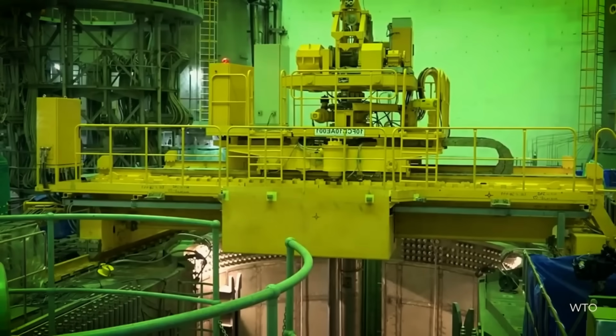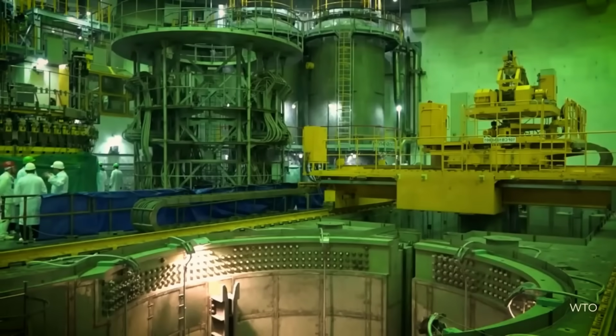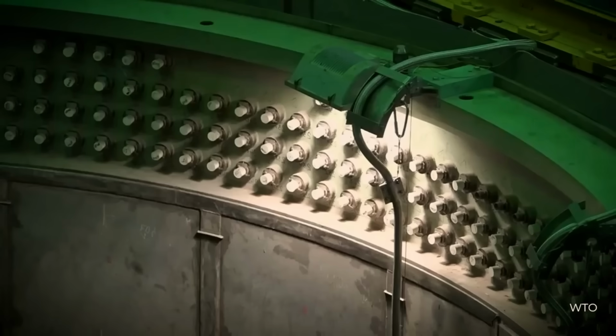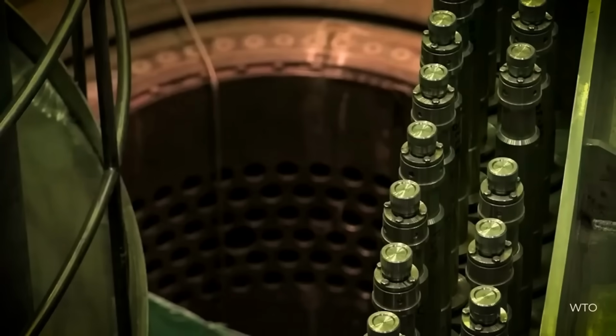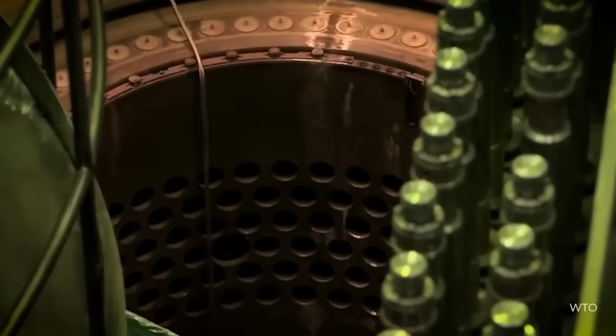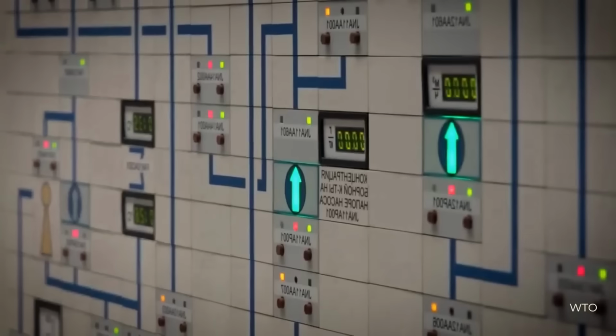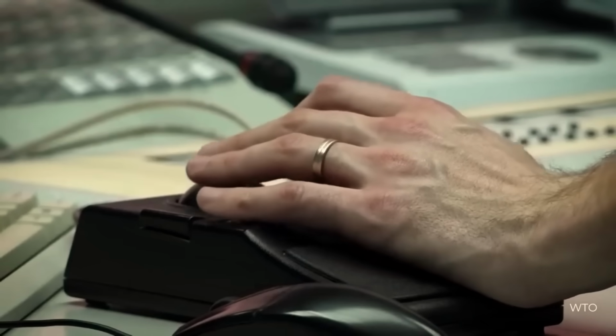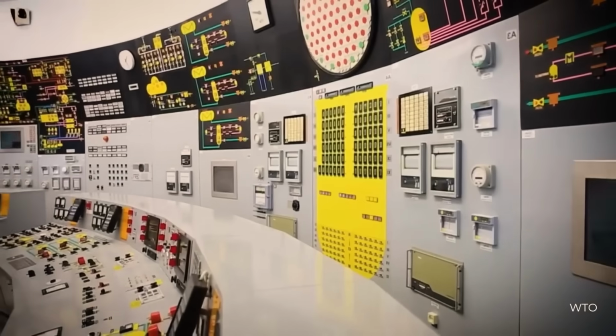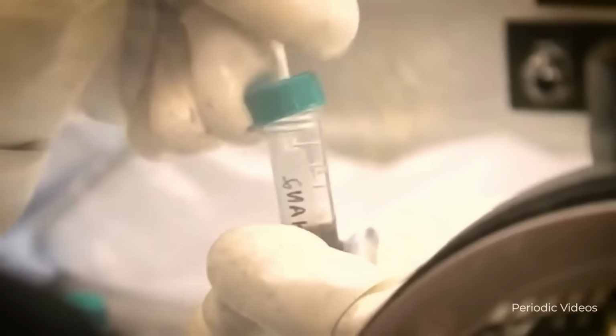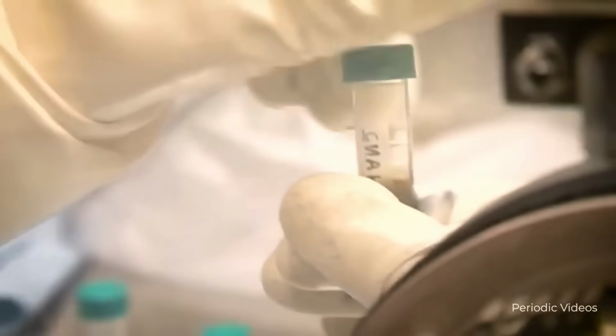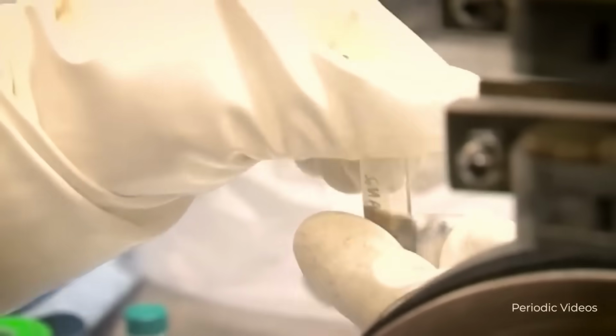These pellets must be uniform to withstand the extreme conditions of irradiation, with a standard as strict as assembling components in a Swiss watch. Each pellet undergoes thorough quality control in a sealed chamber. 4 precision lasers measure the diameter in 2 different points with a tolerance of 5 microns, while a vacuum device equipped with optical sensors verifies the length. Atomic emission spectrometers analyze the chemical composition to detect impurities such as carbon, iron, or magnesium, which could alter the